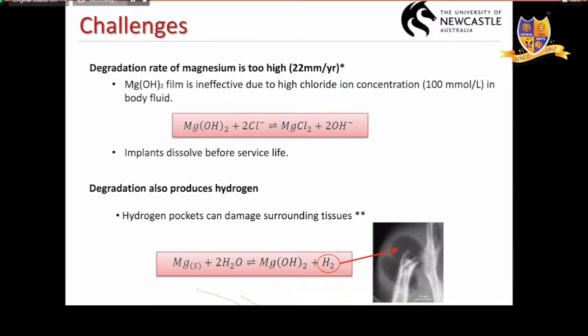To just give you an idea of what it is, in fact, you could glow a bulb by using magnesium degradation. What I mean is, magnesium dissolution is an electrochemical reaction, right? You have an anodic cathodic reaction. You can form a battery out of a magnesium rod in an aqueous solution, and you can glow a bulb there. It is that high. And in fact, in recent years, there's been work going on magnesium batteries as well. With this rate, the implant will dissolve before service life, right? And it can't withstand the loading during that period.